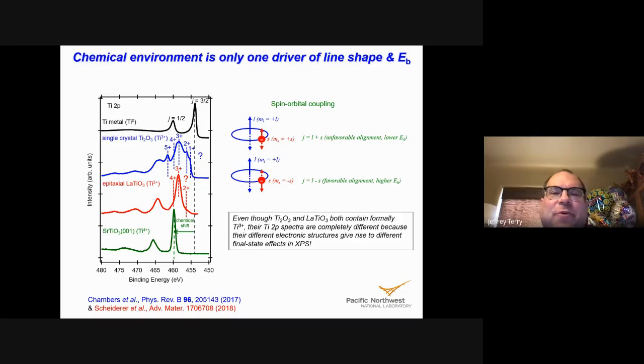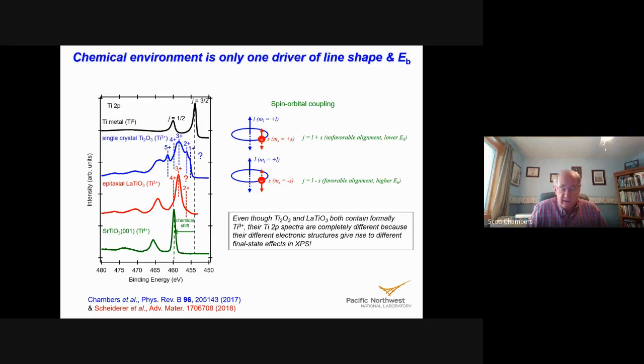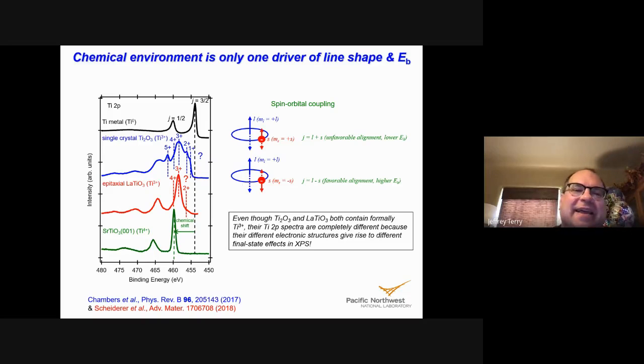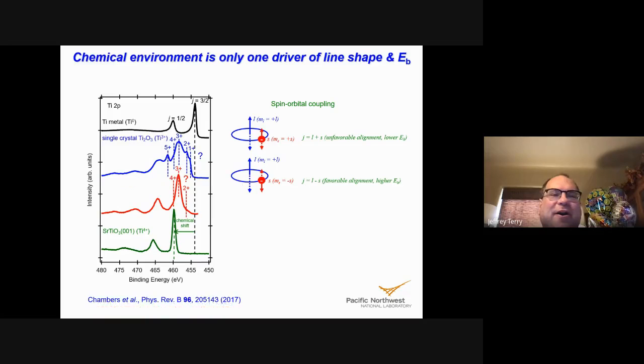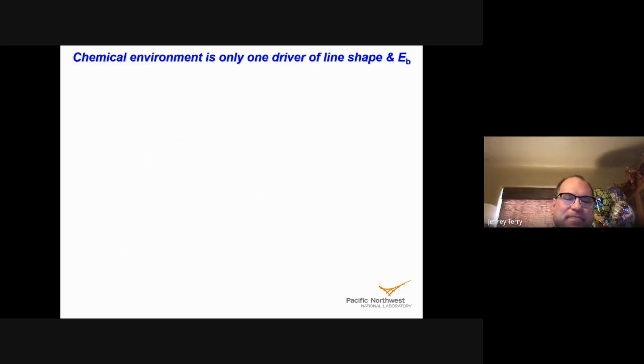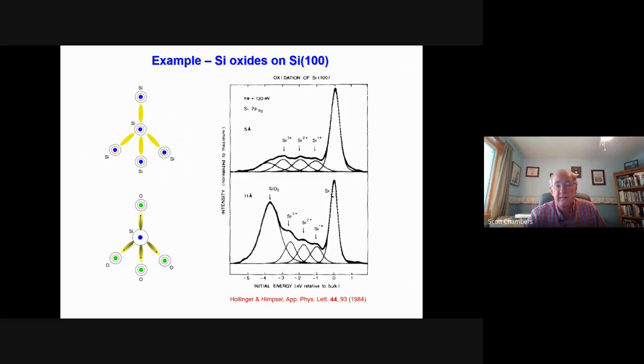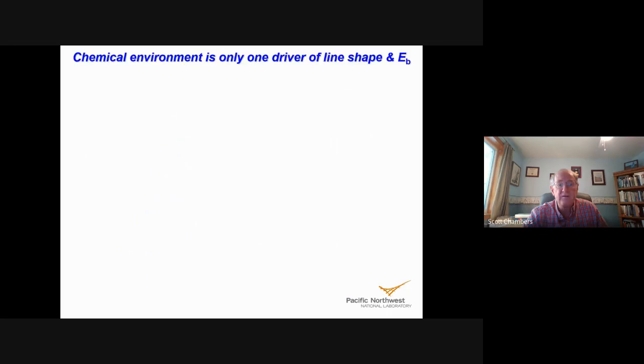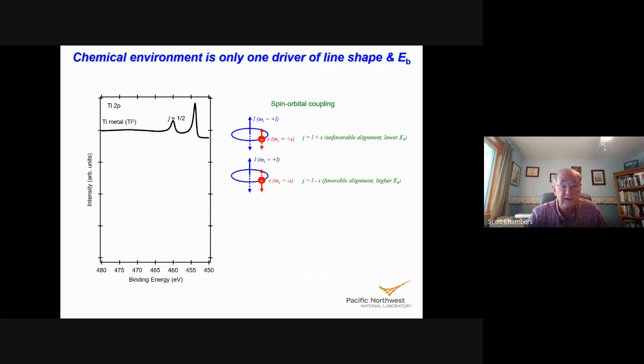Oh, actually, could I clarify one thing? Sure. Since you mentioned this is titanium 2p, that was actually the silicon 2p, correct? And so that had the silicon 2p 1/2 spin orbit component numerically removed from that data, correct? Exactly. Yeah, I should have mentioned. So the silicon 2p is just like the titanium 2p in that regard. It has the spin orbit coupling. Just to point out, the spin orbit splitting between the 2p 3/2 and 2p 1/2 in silicon is only about 5/10 or 6/10 of an eV, compared to here where it's several eV. So it's easier to spot here.